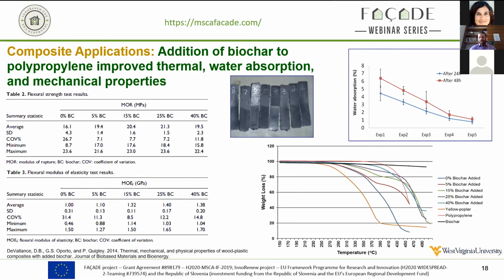Then we're showing the water absorption up here. Experiment 1 is 0% biochar, experiment 5 is 40%. We're just soaking these samples, and you can see that when you add this biochar, these wood plastic composites aren't uptaking as much moisture as they were when you didn't have it in there. And then in the bottom, we're looking at weight loss. So if you're trying to improve the thermal properties of this material, adding these different levels of biochar can actually increase its thermal performance. In a structural sense, you wouldn't maybe get as much deformation or creep under higher temperatures if this material is outside being heated by the sun, let's say.